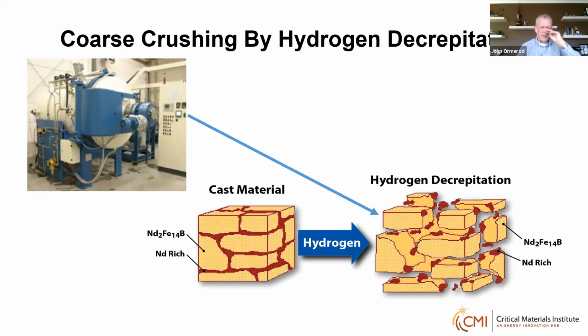And what we do here is we take the strip cast material, put it in a vessel, and apply hydrogen pressure. The hydrogen is readily absorbed by the neodymium-rich phase at the grain boundaries. The lattice expands, and literally the material falls apart and produces a very friable, brittle, coarse powder that is very readily milled and produces high milling efficiencies in the subsequent process,